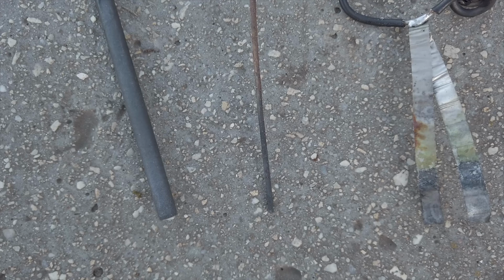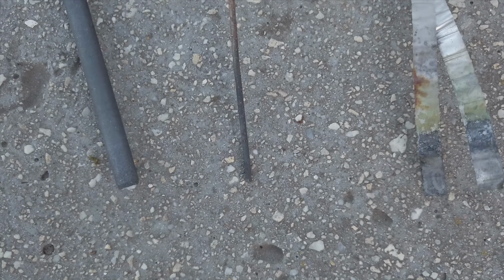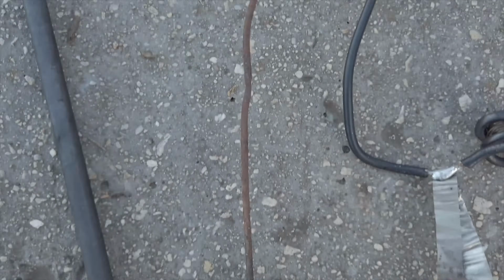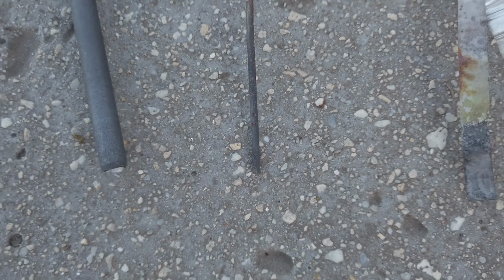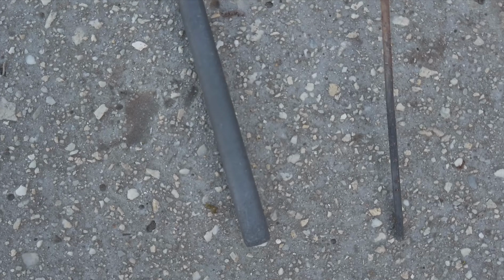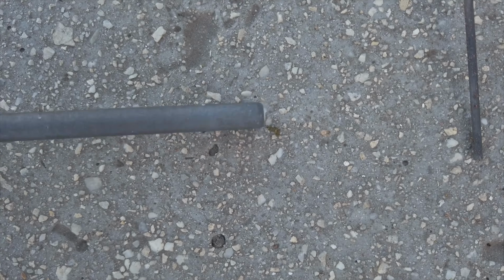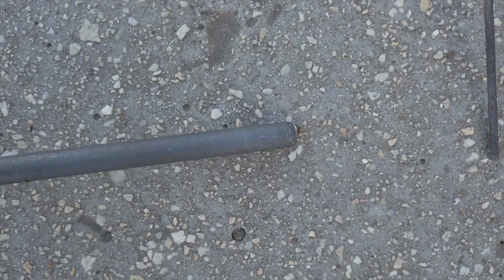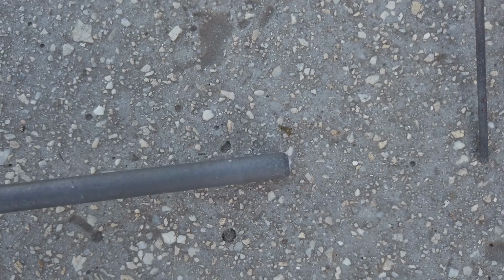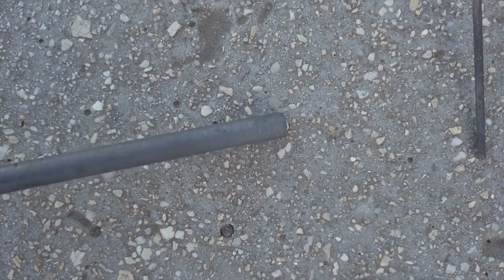Iron, however, or steel, seems to have done perfectly well. I mean, you can see there's no real attack on the electrode, save for a little bit of oxidation on the wire above where it was in the melt. The actual end of the electrode is looking perfectly fine. It hasn't been touched. The real winner here actually was the graphite electrode that we used to generate the chlorine gas, because if we actually have a look here, you can see that there's pretty much no erosion at all on the electrode, despite the fact that it was generating chlorine gas at a temperature of 350 degrees for over an hour at a current of over 6 amps.